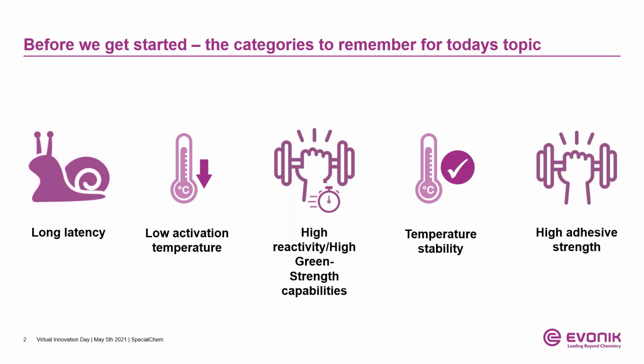These are in particular a long latency or shelf life of the final formulation, ideally combined with an activation temperature that is as low as possible, and also important, high reactivity above activation temperature and the capability for green strength development, as well as excellent properties of the cured adhesive such as high temperature stability and high adhesive strength. Before we proceed, these are the 5 points to take away from this presentation, basically.